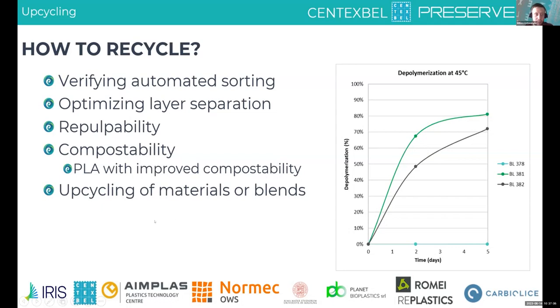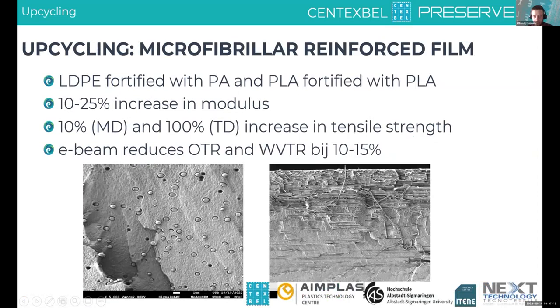And then finally, the final way to recycle the materials is to also upcycle different blends of materials together into new materials with improved properties. An example of this upcycling is using microfibrillar reinforcement. What we do here is we take a blend of polyethylene and polyamide. This can come out of, for example, a recycling process where we were not able to fully separate these materials, and we are processing them together in order to create a new foil.